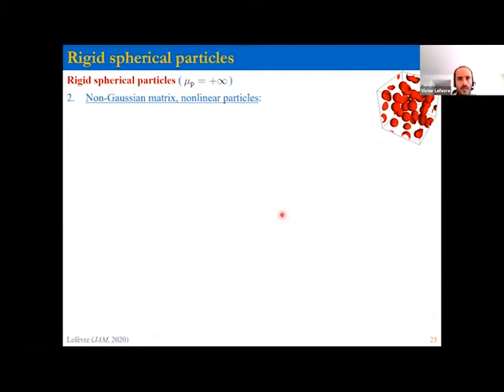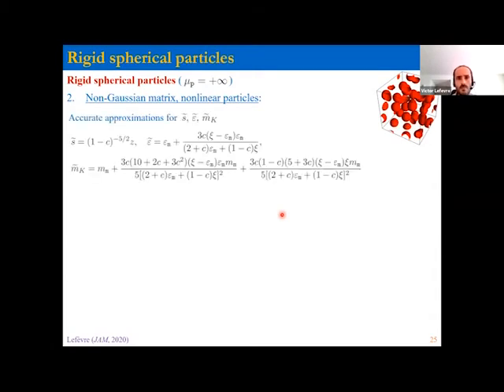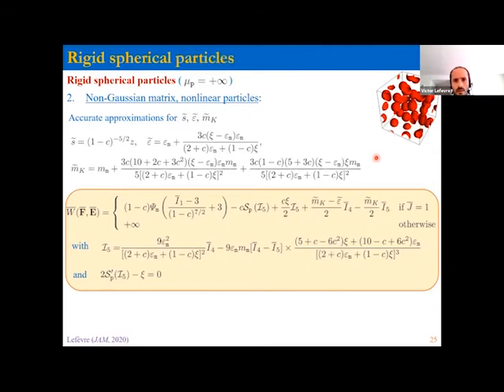It's fully explicit. So now for a more general case of a non-Gaussian matrix, nonlinear particles, so arbitrary choices for psi m and sp, we're able to work out approximations for these three coefficients that appear in the formula. These are specific to the case of rigid spherical particles. And when you put everything in there, again, it's much simpler than it looks like. It's fully explicit up to this one nonlinear algebraic equation that you need to solve on the loading path that you are following. But nonetheless, it's very easy to implement in finite element software, so you can use this model to look at boundary value problems for these dielectric elastomer composites.